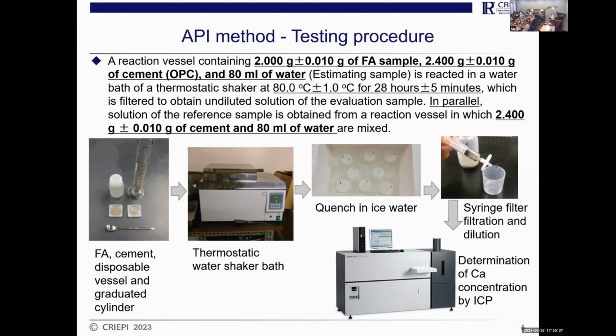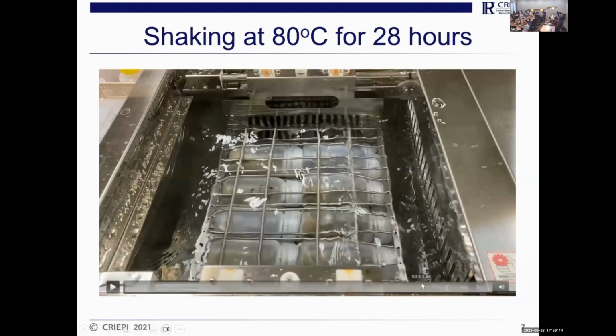And after 28 hours of curing, we take out the sample bottles and quench them in ice water. We need to cool down quickly. And after that, using syringe filters, we must have a filtration. And after that, we need to dilute it to suitable conditions for each equipment, like ICP. I'll show you that small movie like this.